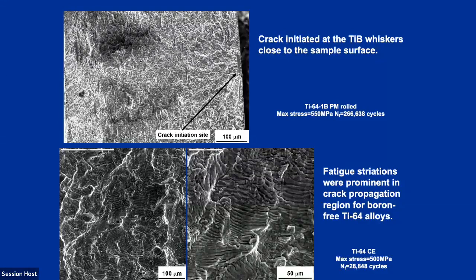And we did see some fatigue striations. There wasn't anything too surprising in this, but it wasn't terrible. That initiation was always something that was a detrimental effect at the TiB whiskers.